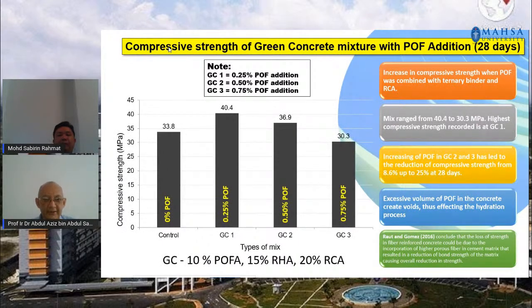This is the compressive strength of the green concrete mixture with palm oil fiber. As you can see, the results are tremendous. All of them achieve more than 30 megapascal, but the best result shows at 0.25% palm oil fiber. The result shows a whopping value of 40.4 megapascal, very much a 10 megapascal increase from the target strength of 30 megapascal. Even at 0.75% of palm oil fiber, the green concrete shows good results of 30 megapascal. All in all, the result shows good performance in compressive strength.